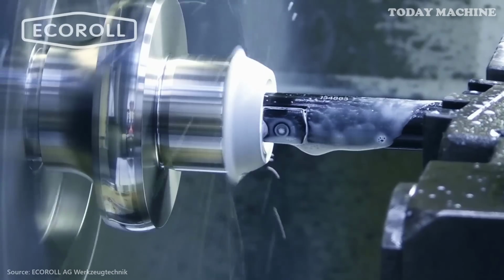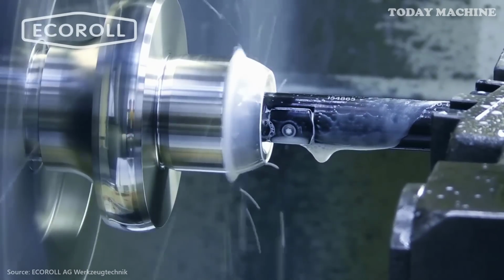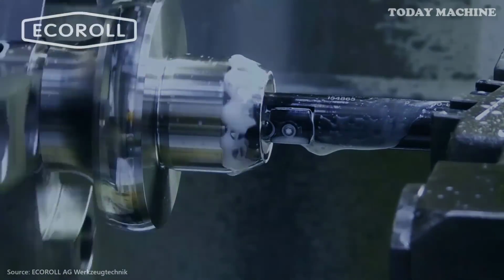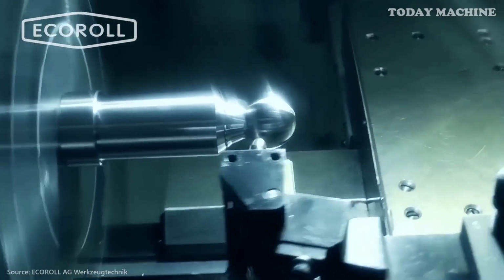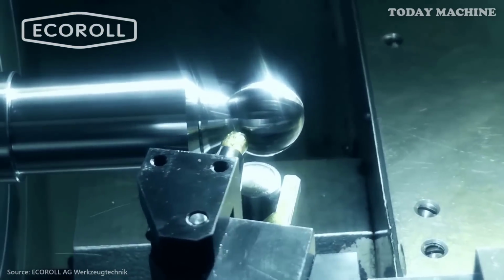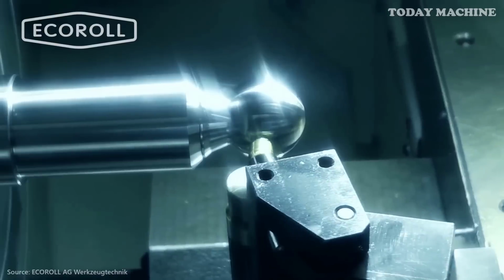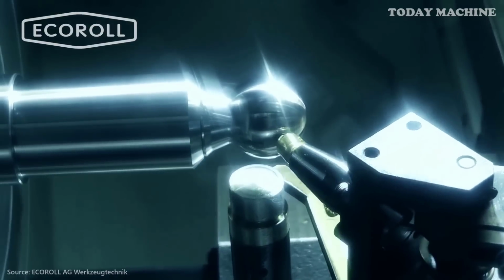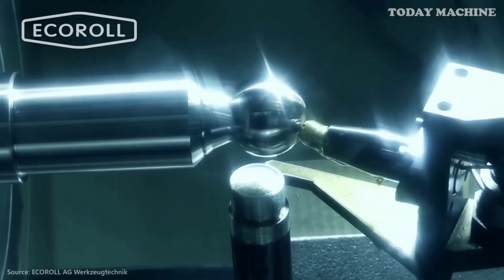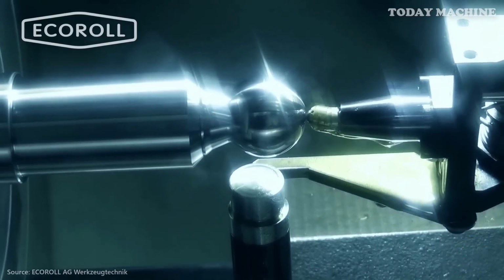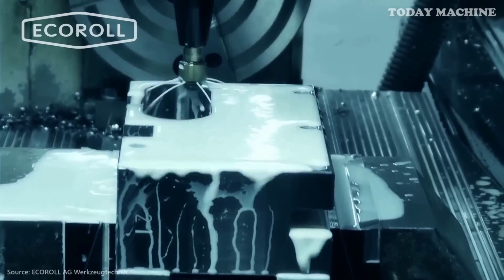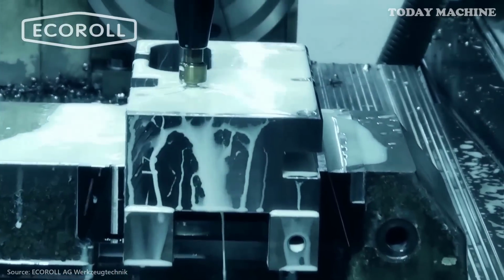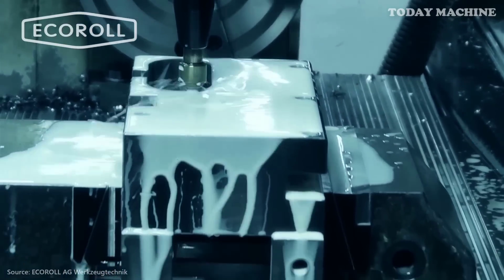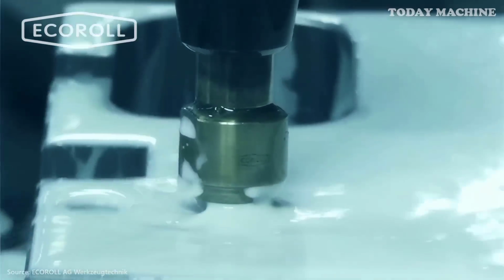For deep rolling, the hydrostatic tools apply controlled compressive forces to induce residual compressive stresses into the surface layer of the component. This enhances fatigue strength, reduces stress corrosion cracking, and extends the component's lifespan. The non-contact nature of hydrostatic support minimizes tool wear and enhances precision, even under demanding conditions.